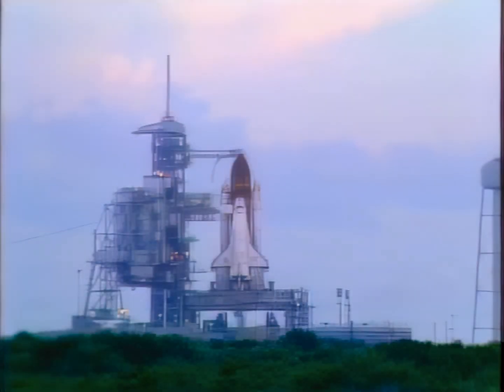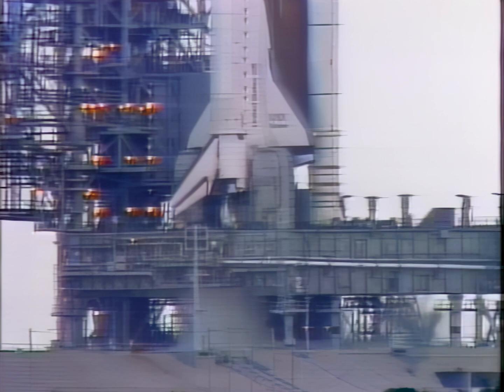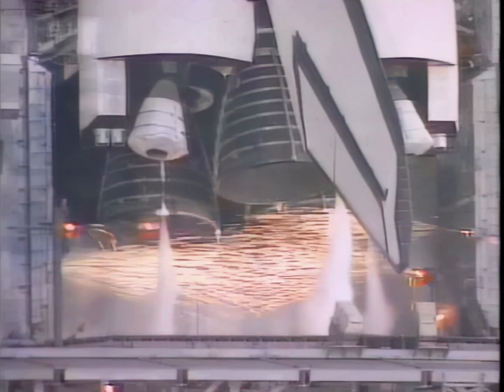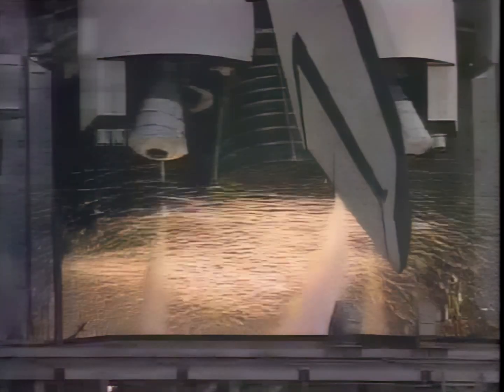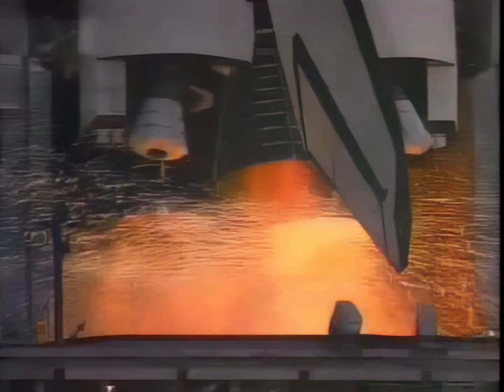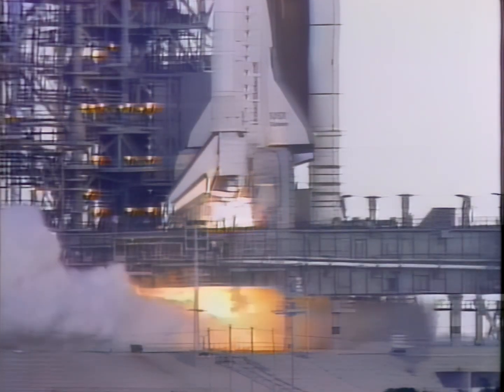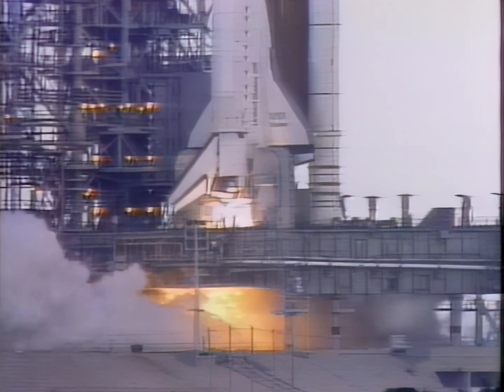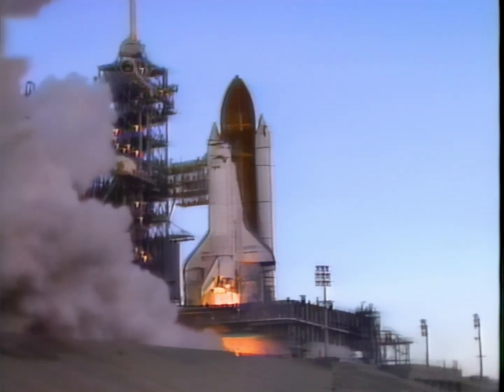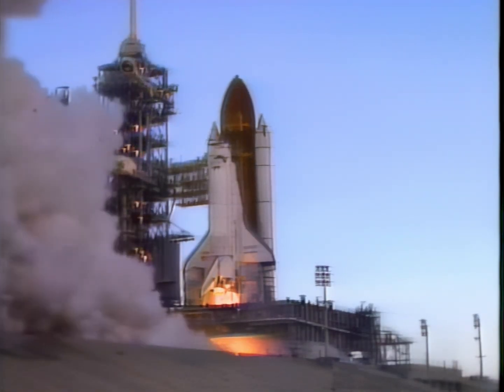The problem this combustion liner is experiencing is the copper alloy is deforming due to the very high temperatures and the stresses that are generated in the thin inner wall, causing the inner wall to deform and actually crack, and the liquid hydrogen is leaking out. We are putting tungsten fibers in the inside layer of the combustion liner to selectively strengthen the inner wall of the combustion liner.